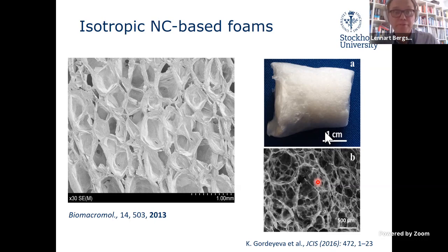Produced by evaporative drying, this is early work done together with Lars Berglund and his group, where a Pickering foam was made using a short chain surfactant, octanol or octanoic acid, which provides the particles with some hydrophobic character. In this case, in my work, we were also using calcium as a way to precipitate or strengthen the network to resist the stresses during evaporative drying.